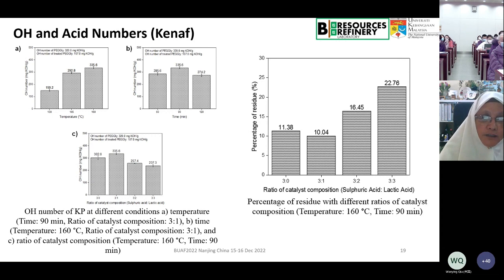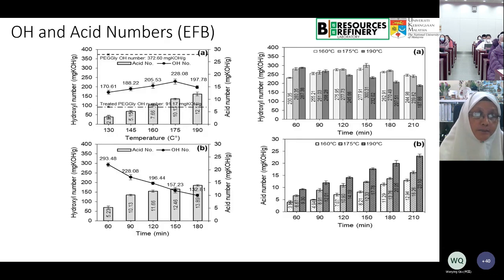with the ratio of catalyst composition from 3 to 0, without lactic acid, then 3 to 1 lactic acid, 3 to 2, and 3 to 3, the percentage of residue is reduced, and this gives different OH numbers. The OH number is very important when you want to make PU, because the number will contribute to the properties of the PU, depending on how much the OH will react with isocyanate in the process of making polyurethane. For the OH and acid number for EFB, the same thing will happen.